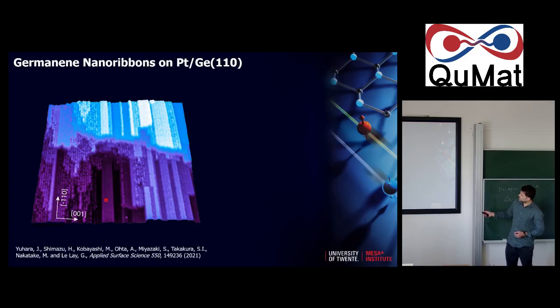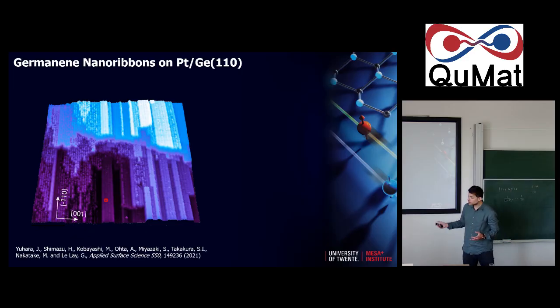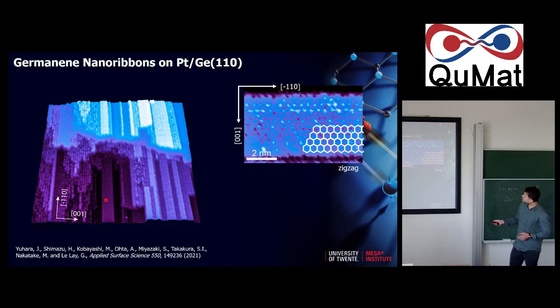We have looked at the structures. We can draw them in quite a consistent way, and they look a bit like this. I don't know if it's so visible with the contrast, but I hope you can see it. And if you now zoom in on top, we also have seen that this phase is a germanium phase on top of platinum, and it's a growth that is also matching experiments that were done with silver. So it's a process that can be done not only with platinum but also with silver. And the reason is that germanium simply likes to go on top of the platinum. More of the platinum likes to travel between the germanium surface layers.